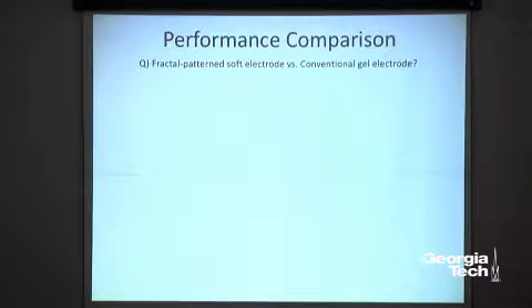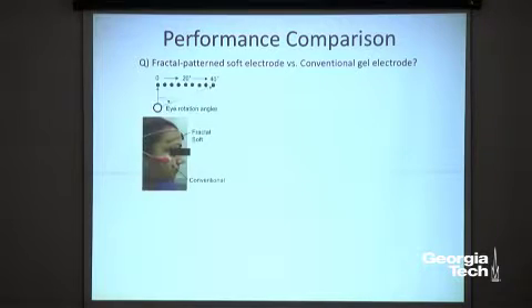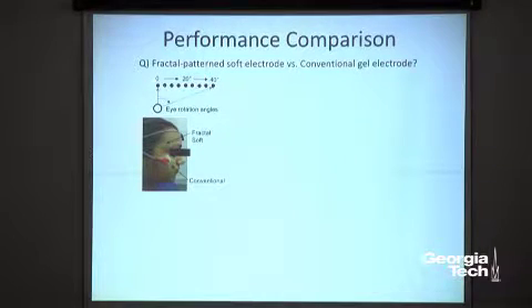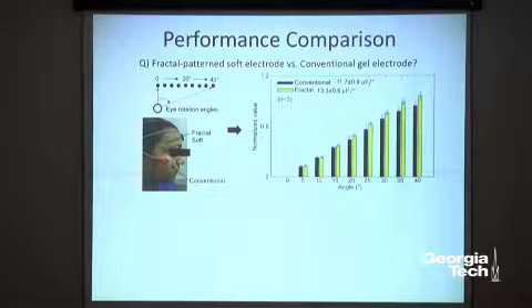Then we had this performance comparison to see whether our soft electrode is as good as the conventional gel-based electrode. So this person is wearing two types of electrode at the same time, and I asked her to move the eye from 0 up to 40 degrees. And we measured the electrooculograms. As you see, as the eye moves further and further, you have this increase of biopotential. So about 11.7 microvolts per degree for conventional, and about 13 microvolts per degree for soft electrode. So interestingly, even our soft electrode has higher signal compared to the gel-based electrode.